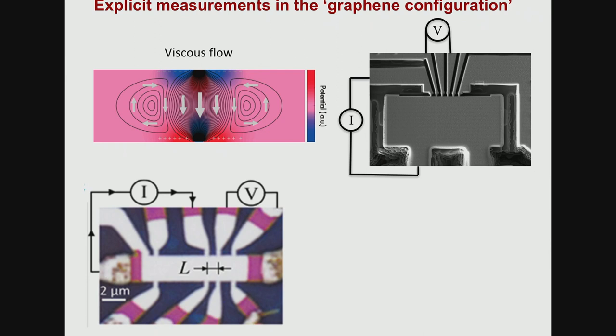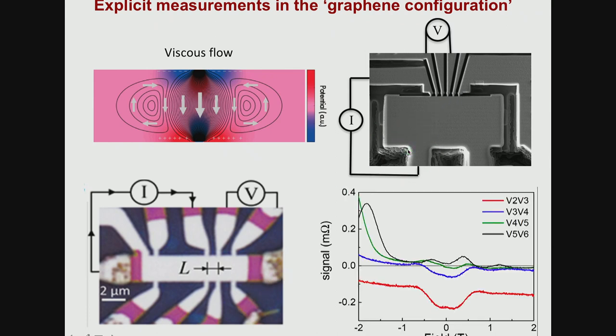We, very naturally, once they'd published this beautiful negative resistance experiment, wanted to check the negative resistance experiments on our samples. So this is palladium cobaltate, made to very similar overall shapes and dimensions to theirs. And we were delighted to see we're doing some field experiments here, but the zero field result is what counts. At zero field, we are seeing negative resistance, and we're seeing the size of the negative resistance go down as we make the contact separation from the contact point bigger. And that's exactly what a viscous theory predicts. So again, we could easily have gone to press and say, okay, fantastic. We can confirm this result from graphene.